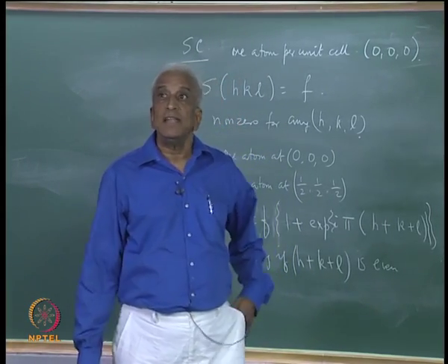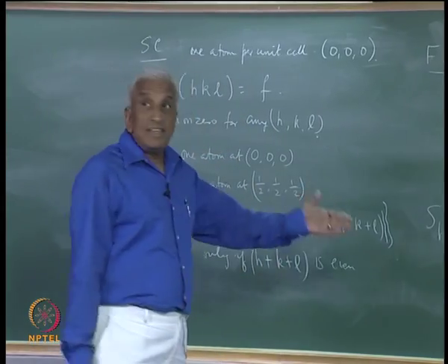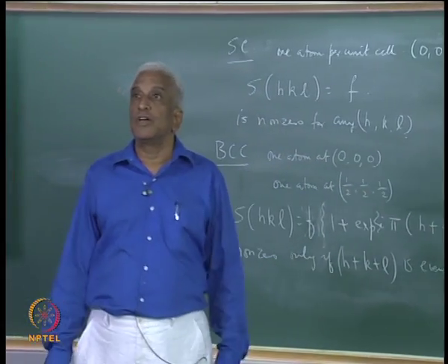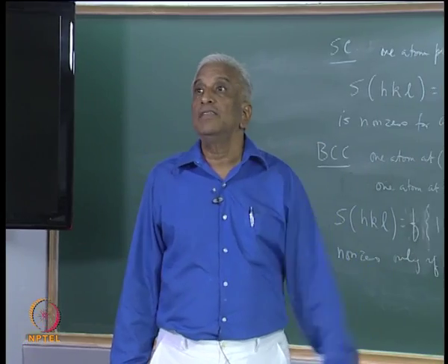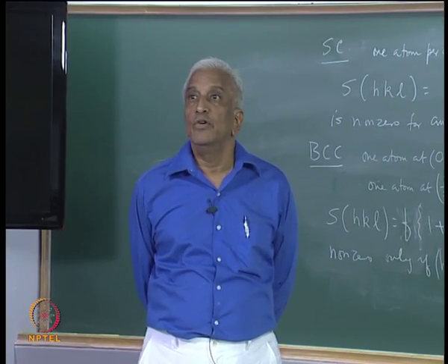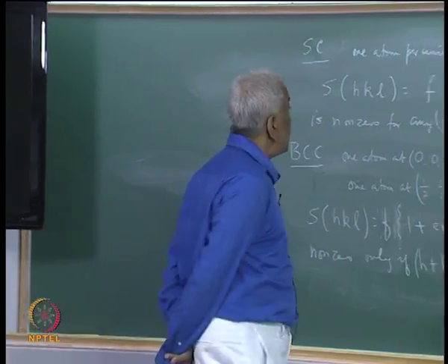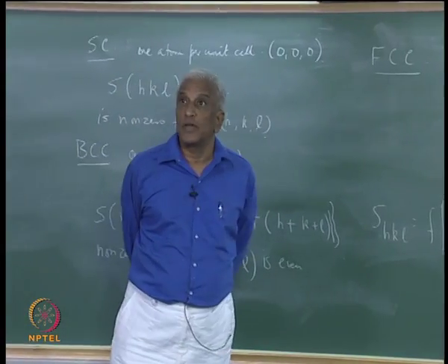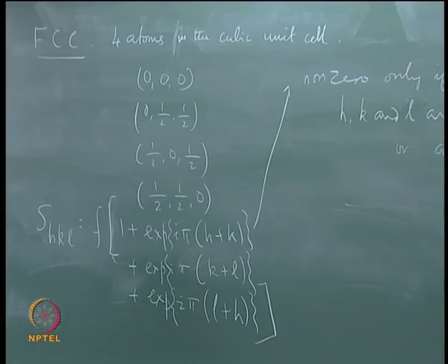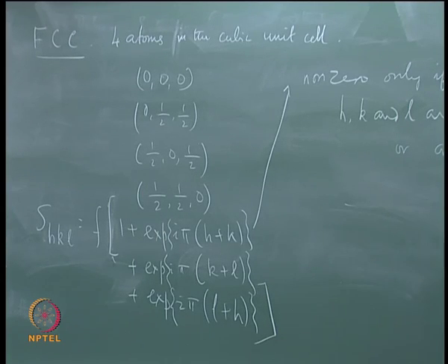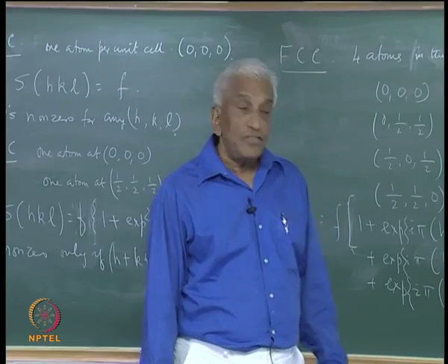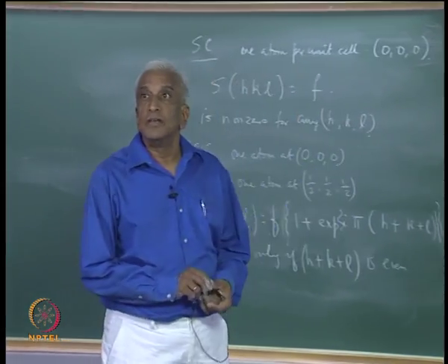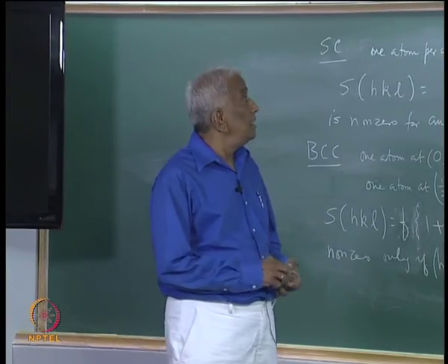So, the experimentally calculated ratios, knowing these h square plus k square plus L square values, you can calculate the ratios of sin square theta values, and so we can compare the h square plus k square plus L square values and the sin square theta values. The lattice type is immediately found by matching these ratios. So, that is how the analysis is done for the Debye-Scherrer method.